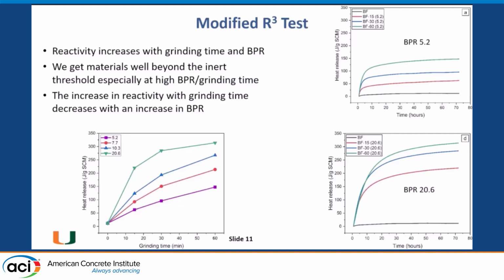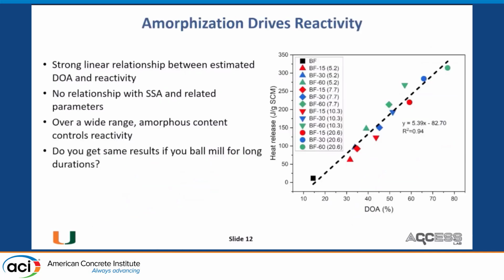And from these R3 and similar tests, the threshold is about 100 joule per gram of SCM. And you can see that, beyond a certain grinding time or beyond a certain BPR, you pretty easily exceed the level of reactivity needed. So again, with increased grinding time and increased BPR, the reactivity increases.